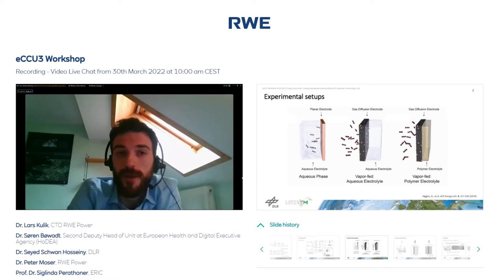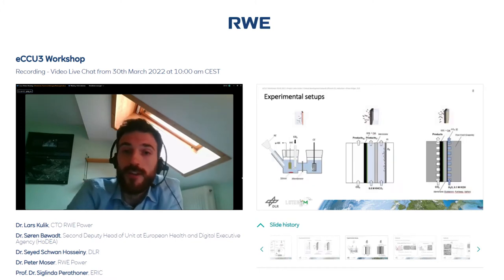On slide 7, there are the experimental setups. I think also Schwan has used this diagram in the morning, but it's anyhow important to mention again that there is a transfer from a rather fundamental approach on the left side, where we have to put CO2 in a solution and just have a metal surface as an electrode, towards an electrode where we have, for instance, already a gas diffusion electrode where CO2 can come from the backside. This allows us to have much better mass transport of CO2 to the catalyst. And then on the very right side, to change the aqueous electrolyte to a polymer electrolyte, basically lowering the resistance of the cell. It would be similar to the known fuel cell configuration in this case.